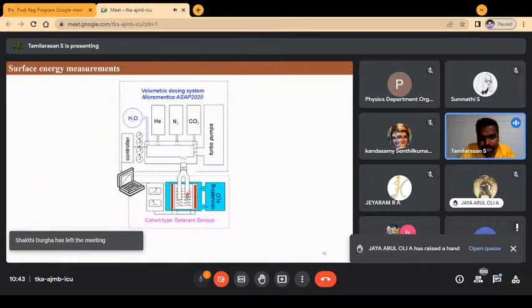What you do, you start to dose whatever solvent you want to interact with the exposed nano surface. Here they say water, but you can do alcohol, methanol, ethanol, and other organics. We are just exploring, because we don't want to expose this manifold to corrosive gases, but we can do several different adsorbates on the surface. And when the exposed surface comes in contact with the adsorbate, it's going to adsorb and give off heat, and it's going to get quenched exothermically. So you get an exothermic peak which you can measure and quantify, and from that you can get the surface energy.